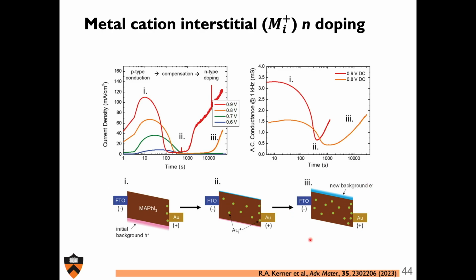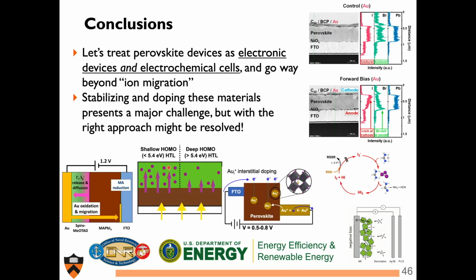And the photoluminescence that I'm not going to show here also agrees with this. We get PL that sort of goes down when I enter this compensated region, when bimolecular recombination is really bad, right? When I have almost no electrons or holes around. You see that a low in conductivity is also associated with a low in PL. And so in conclusion,